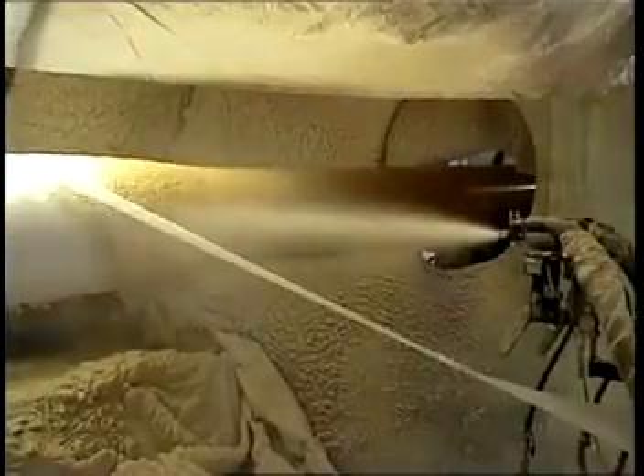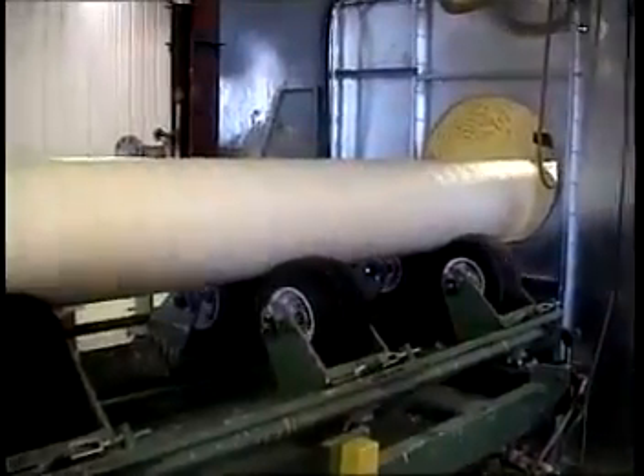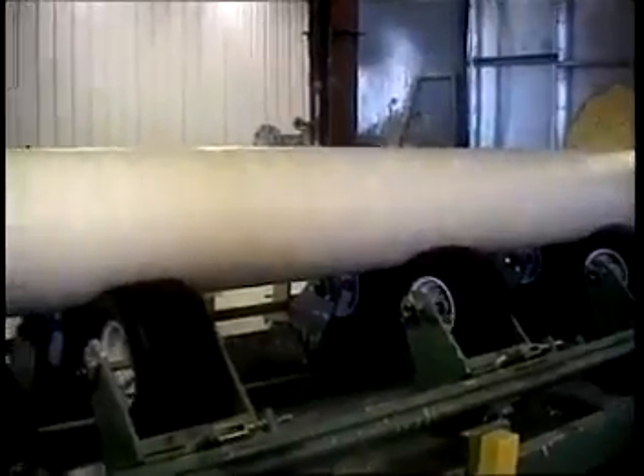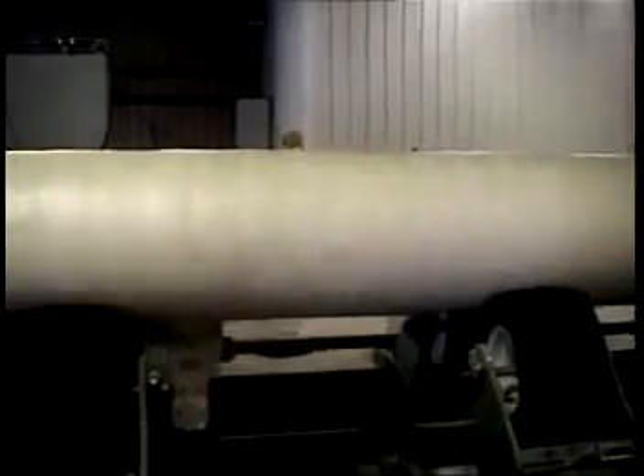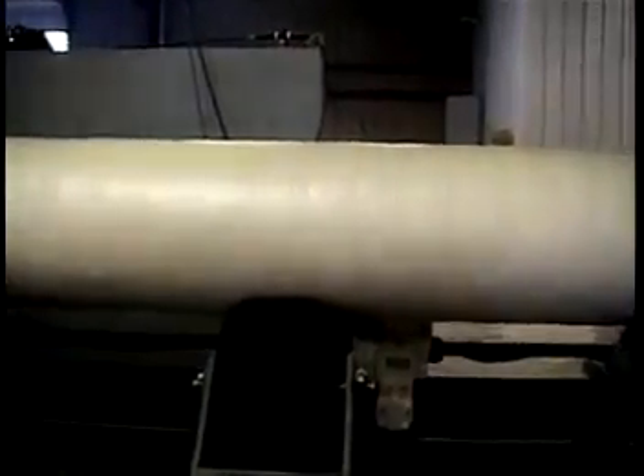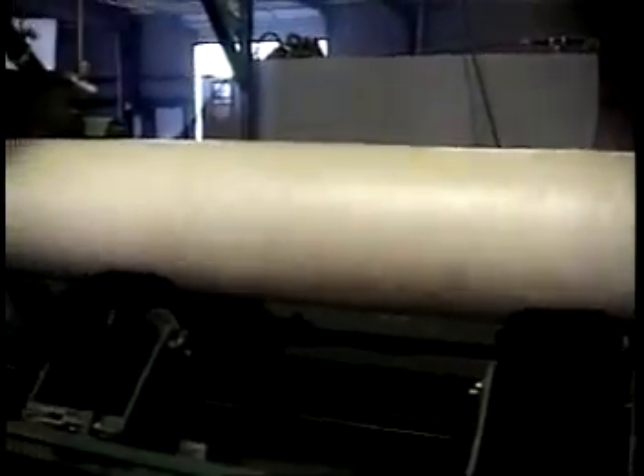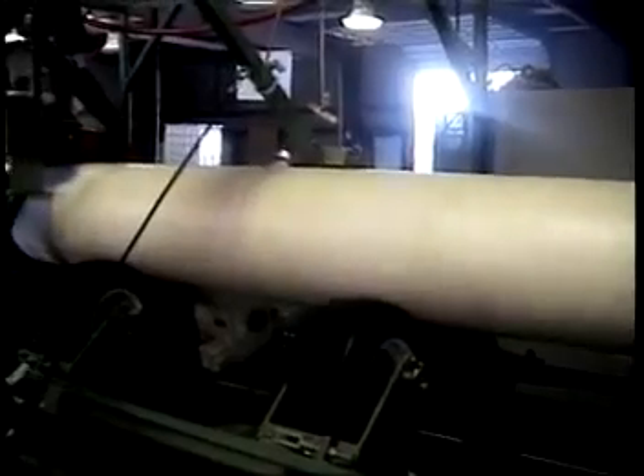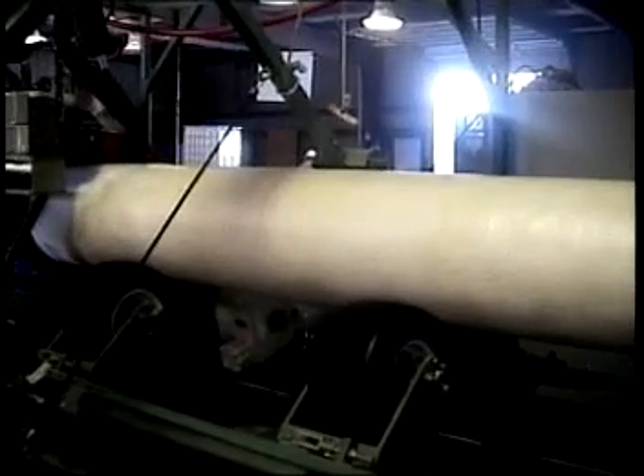In the spray booth, polyurethane foam is sprayed onto the pipe in one pass to the required thickness of 2 inches. The cure rate is controlled so that the foam is fully risen before application of the polyethylene bonding sheet. The foam has adequate compression strength to support the pipe as it passes along the outfeed conveyor. The foam continues to cure and build strength during the entire process. The speed of the system is approximately 8 feet per minute.